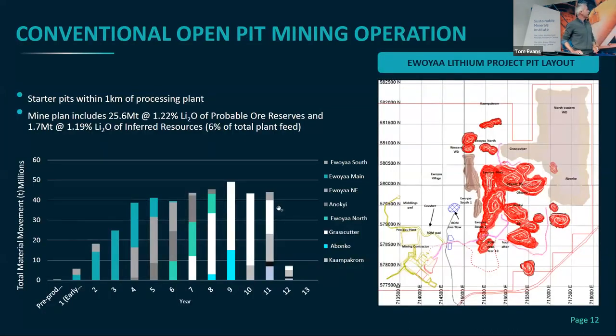And then simple mining. So we saw the cross sections. So this is an open pit mining operation from surface. I think the deepest pit goes to roughly 230 meters below the natural surface. Life of mine stripping ratio around 12 to 1. The early years much lower at 3-4 to 1. So a simple mining operation that's then scheduled to get that P1, P2 mix correct through the mill feed to maximize recoveries. And obviously from the trucking scenarios point of view.